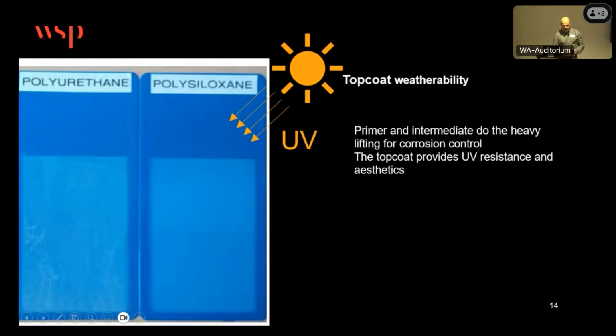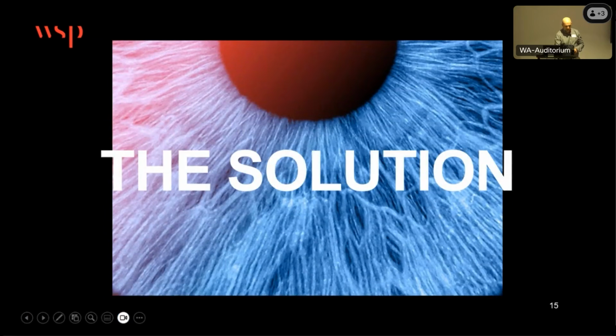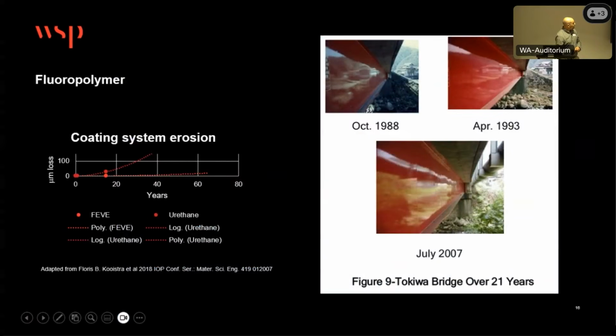So on the project, really, weatherability and ability to resist UV were the critical factors for the coating that we selected. And that solution is a 3-coat paint system based on fluoropolymer. Fluoropolymer is a resin that was developed in Japan in the early 80s for infrastructure and marine structures. And it has demonstrated performance of over 35 years with regards to UV resistance and resistance to very hot and humid tropical environments.